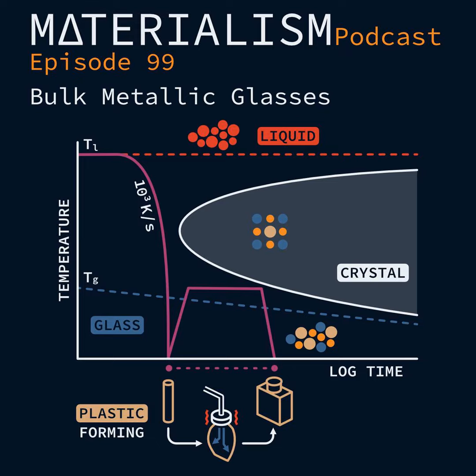So the absolutely outstanding property about metallic glasses is that we talked about their room temperature properties that even exceed those of the best metals. And when it comes to processing now, they can almost be processed in the same way as thermoplasts are processed. Exactly what you said, Andrew, that you can take them and heat them back. So you cool them to room temperature. Now you have a simple shape, a disc or something, and now you can heat it up. You avoid this TTT diagram. You heat it up, and then once you're in this temperature region, you can deform them. And if you want to deform them at lower force, you go even a little higher. The time shortens. But the time windows are very practical. You have about minutes, and you can deform them easily with very little force.